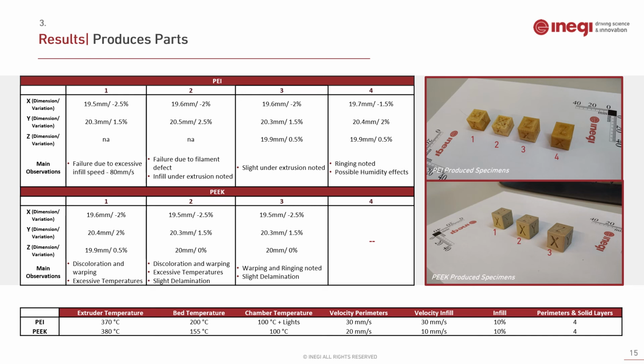Concerning the PEEK produced parts, after 3 trials and some adjustments, we were able to produce parts that we deemed reasonable. The best printing setup experimented is the one described in the table at the bottom, in which we have the extruder temperature of 380 degrees, a bed temperature of 155 degrees, the chamber temperature of 100 degrees without the light system, a velocity for perimeters of 20 mm per second, a velocity of infill of 10 mm per second, an infill of 10%, and 4 perimeters as solid layers. The defects noted in the best part produced using PEEK were a slight warping effect and slight delamination. Apart from that, we also noted some consistent dimensional variation in the parts and some ringing effect.